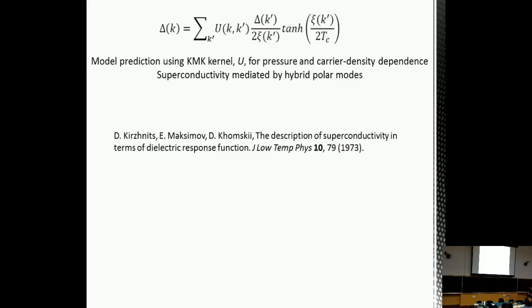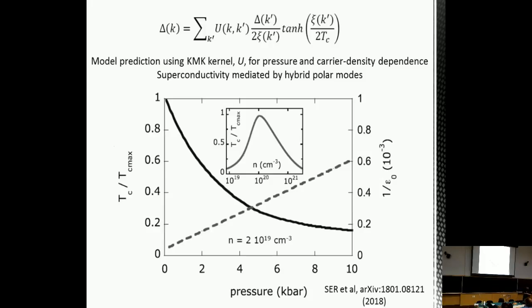So if we go through this model, we get a picture that looks like this, where the Tc versus carrier density has a nice dome structure, which is recreated here. And also, we have the fact that Tc is strongly suppressed as you increase the pressure. So that seems to be fitting quite well with measurements. And again, in here, there's no adjustable parameters. There's just the zero temperature parameters for strontium titanate, which are measured from independent experiments. And for a reasonable choice of model parameters, we get that Tc comes out to be around half a Kelvin.